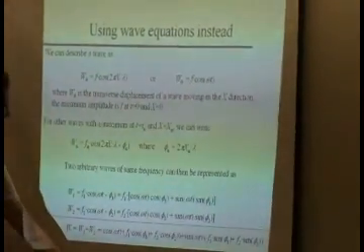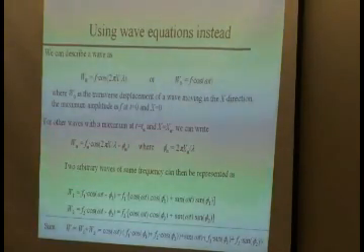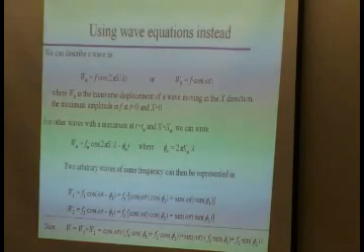Can you do the same for the second wave? Sure. Could you do the same for 10 waves, 20 waves, 100 waves? Yeah. What you will see is that all of them have some common factors. All of them have this cosine omega t and the sine omega t, right? And so when you sum these waves, you can actually get an expression where you say cosine of omega t times the sum of all these f's, of all the amplitudes, times the cosine of that phase, plus the same thing for the sine term. Okay?